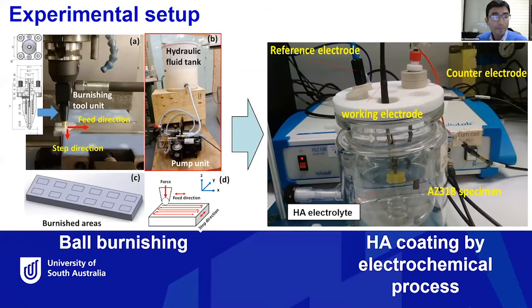Looking at the experimental setup, this is the setup we have here. We have taken a magnesium plate of a certain thickness, and then considered a specific test coupon. Then we did the burnishing. This is our burnishing tool, where a small ball is controlled by hydraulic pressure, and you apply the force onto the magnesium material. You can control the force, and also the feed rate, how fast the ball is rolling onto the material. You can also change the step. We have taken a zigzag burnishing path to modify the surface.